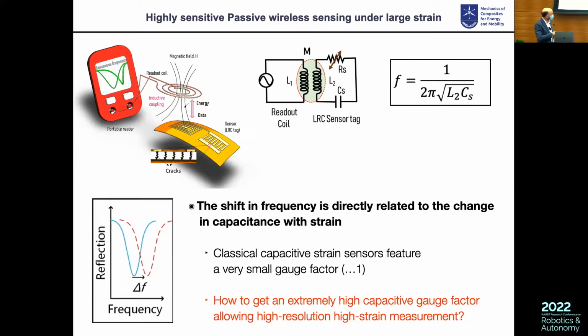The main problem is that if you look at all the capacitive sensors that exist on the market, they have a very small gauge factor. Not extremely small, but it's close to 1. It is only due to the geometrical change due to the extension of the sensor. And this makes a gauge factor that is close to 1. Small gauge factor means that you have a very small shift in frequency on that curve, right? And if you want to have a good wireless monitoring for our system, we want to be able to have a big shift here. So we want to increase the gauge factor.